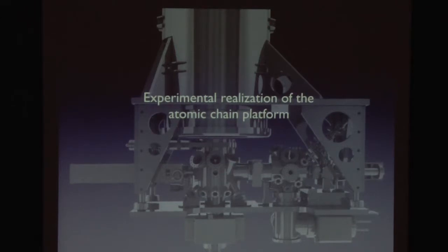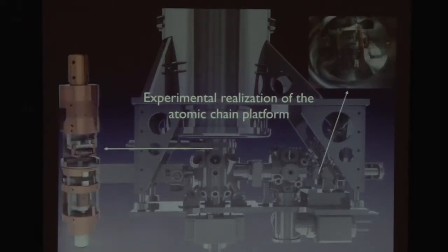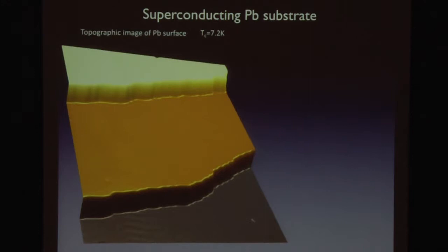So this takes very sophisticated equipment that allows you to do in situ growth in an ultra-high vacuum environment. It allows you to transfer the sample without exposure to air to a very good low temperature STM machine that gives you high energy resolution. You also need the ability to do magnetic measurements on the same structures. So all these different things have to come together to be able to do this one single experiment. Okay, so this has been kind of a tough road. So let me tell you about the pieces.